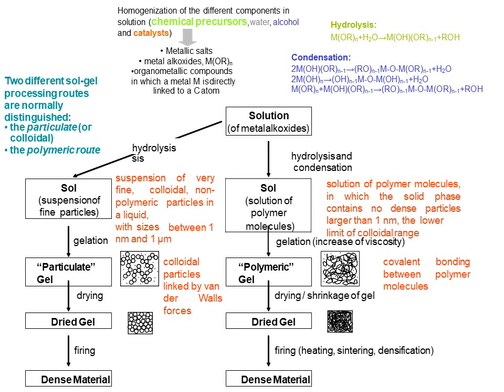After hydrolysis and condensation, a solution of polymeric molecules in which the solid phase contains no dense particles larger than 1 nanometer, the lower limit of the colloidal range, occurs, which is called a solution of polymer molecules. Then in the gelation process, an increase of viscosity occurs, which forms a polymeric gel, in which covalent bonding between polymeric molecules occurs. Then drying, a dried gel is formed, firing, heating, sintering, then a dense material is formed.